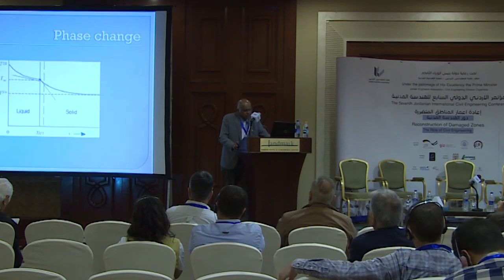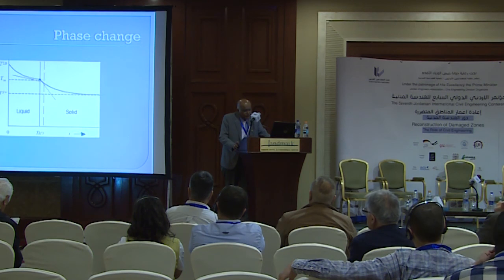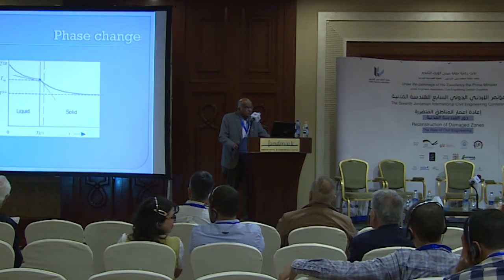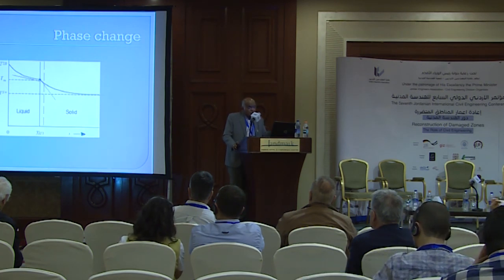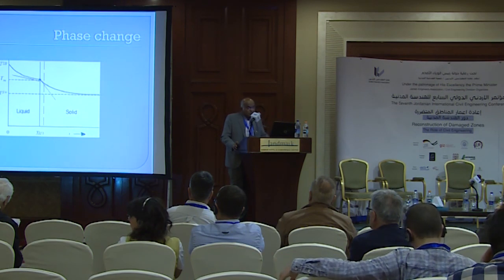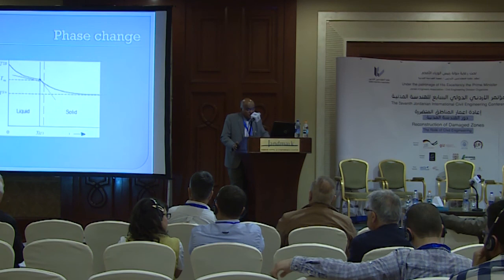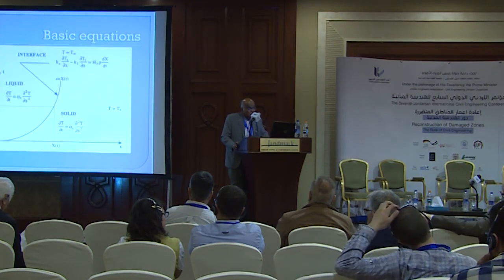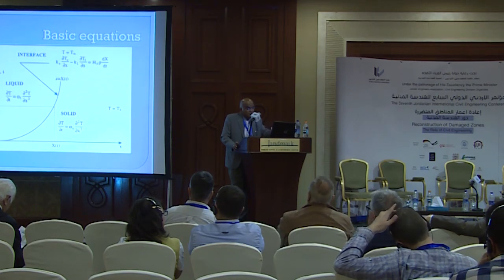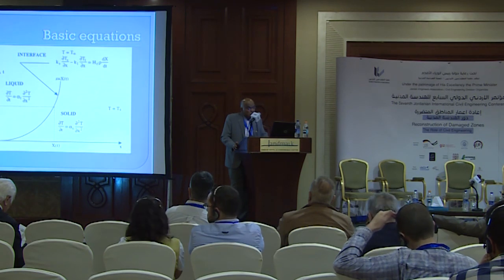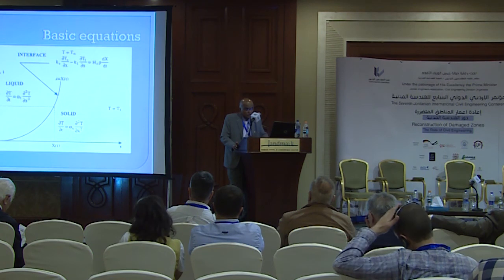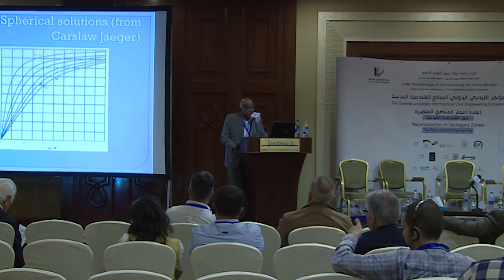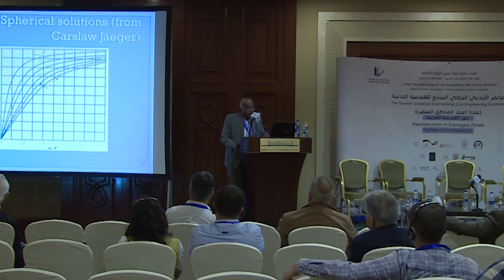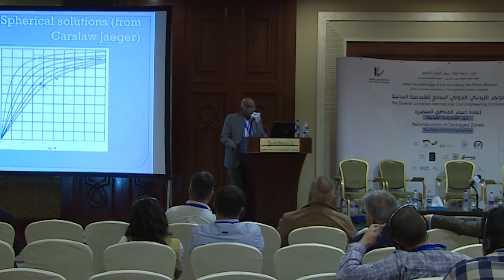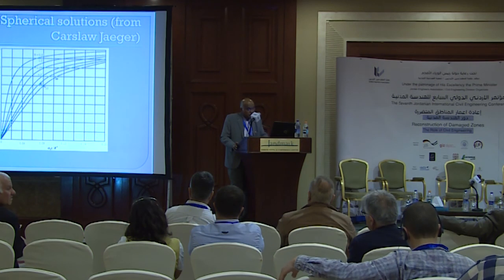Now this diagram here shows what is happening when you have the change from liquid to solid. The vertical line shows the phase boundary, and the tangents are shown by the red lines. So the equation which I showed earlier involves the gradients at the boundary. The dc/dx or dT/dx are the gradients. So on either side of the interface, liquid and solid, we have these diffusion equations. As I mentioned, the pressure term is not included, but you can add it. And these are the classical solutions for the sphere. We have the non-dimensional parameters on the x-axis and y-axis. You see for different combinations how it moves.